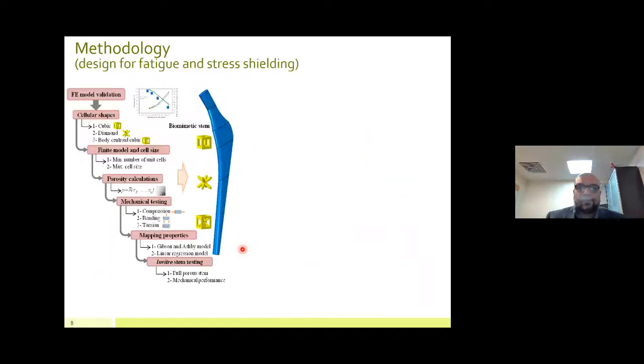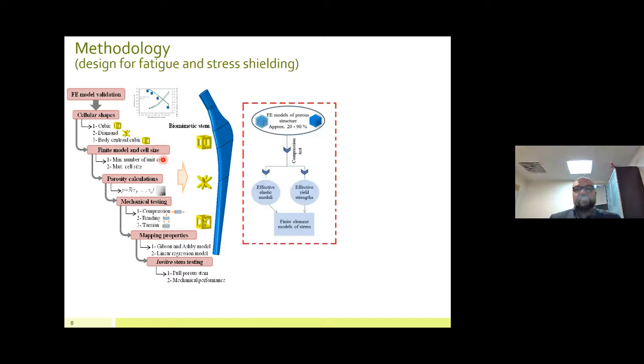The first step was we created a few microstructure unit cells, and then we looked at which of these microstructure unit cells, after going through all this process, are giving us properties which are close to the femur bone. So this is the roadmap that we took, and once we found the properties of the microstructure and the way to design the microstructure to achieve an ultimate stiffness close to the femur bone, that was our design. Then we used that to construct the full implant. So this explains the approach.